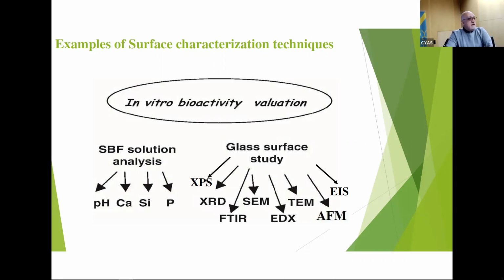Atomic force microscopy is also very important to get information sometimes about the thickness of the coat itself you are using, or to give you information about the hardness of the coating. Is it a hard coating or not? That's atomic force microscopy, which is also a very important tool. And EIS is electrochemical impedance spectroscopy. That's to measure the corrosion resistance of your coat.